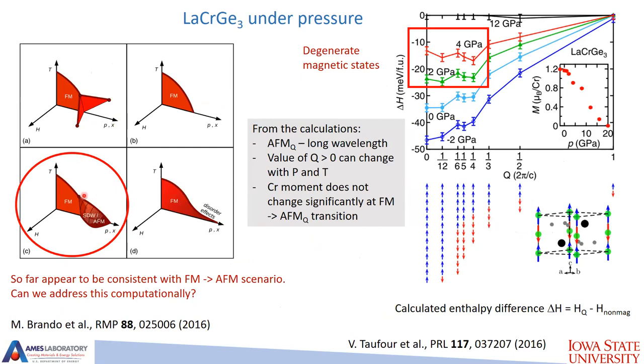One of the possibilities is this scenario, because we don't have magnetic signal after the ferromagnetism. So one of the possibilities is this scenario with a ferromagnetic phase going to SDW or anti-ferromagnetism. We can try to address this computationally, in collaboration with Aiming Ho, C.Z. Wang and their group.